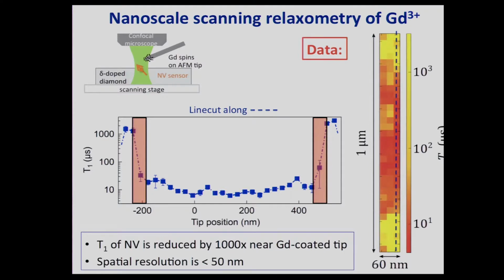We can take a line trace across this data and plot T1 as a function of tip position. And we see that we have a pretty broad feature, but our spatial resolution can be estimated to be about 50 nanometers, which is the characteristic size scale over which the T1 changes by about 3 orders of magnitude across that 50 nanometers.